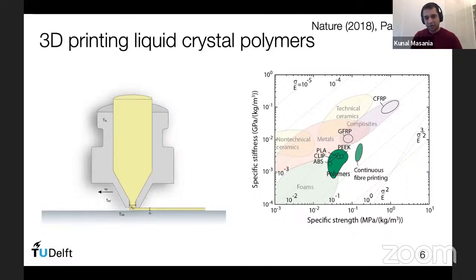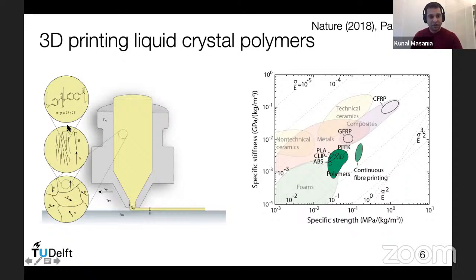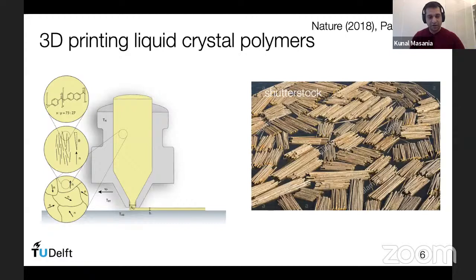And typically what people do with polymers is try to avoid anisotropy by trying to have high temperatures in the build volume and reducing molecular orientation during 3D printing. And we thought, well, instead of trying to combat this problem of 3D printing, why not try to use it as a feature? So what we came up with was the idea to print a liquid crystal polymer. Liquid crystal polymers are a hierarchically structured material. So you have a very simple molecular building block, and these are very short chains of a polymer. And they're locally arranged as a nematic domain, which is oriented locally but isotropic as a global material.